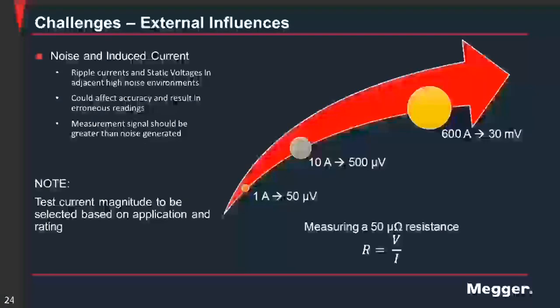And I think this is the last challenge, the external influence challenge from the noise and induced current. When you have a ripple current and static voltage in the adjacent high noise environment, they can affect accuracy and result in erroneous reading. It's very critical to understand that the voltage measured using the potential lead should be greater than the background noise. So remember, the voltage should be greater than background noise. Otherwise, the measurement will be inaccurate.